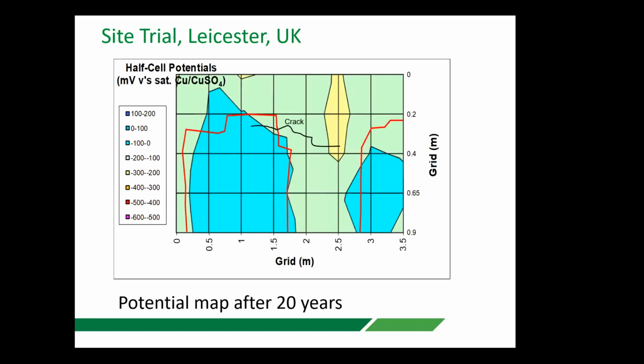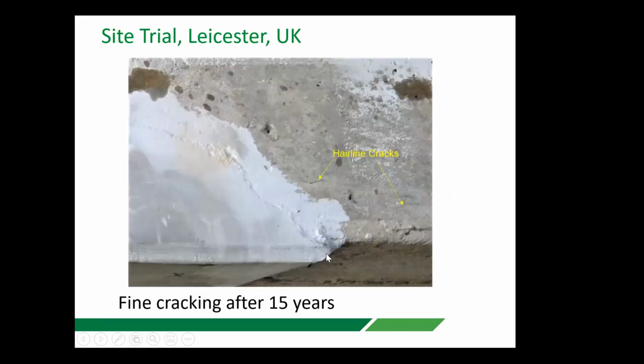Okay, looking again at the potential map at around 20 years. A potential map is when we take measurements of the potential on the surface of the concrete around the patch and beyond. These are the patch areas within that red line, the 2 patch areas. And we can see that the potential within those patch areas was, in fact, positive in some cases. And outside the patch repair, mainly they were below 200 millivolts. But there was an area, quite a distance between the two, that was showing signs of corrosion. And we noticed that there was actually a crack developing within that region.